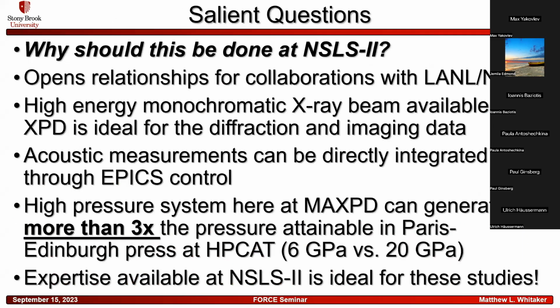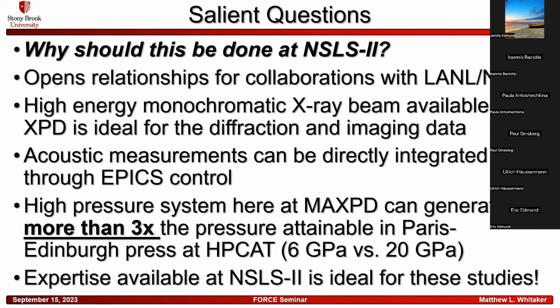So some of the salient questions that we have is why should this be done at NSLS2? And one of the things obviously is that it opens up relationships for collaborations between Brookhaven Lab and Los Alamos Lab. But also the high energy monochromatic X-ray beam that's available at XPD is really ideal for the diffraction and imaging data that we want to collect in these experiments. We typically use a 67 keV beam, which is capable of penetrating a lot of things that lower energy beams are not.